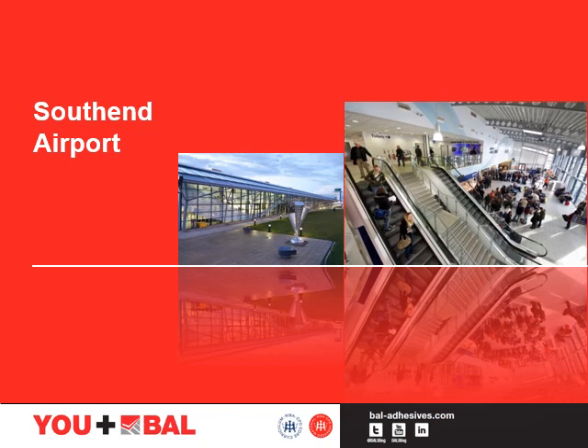London Southend Airport was extended, which included the development of a new departure lounge. More than 5,500 metres of porcelain floor tiles were laid. Floor tiles were laid onto a power-floated concrete finish, a hard-wearing substrate often specified for high traffic areas. Due to the substrate and the heavy traffic use, consideration was needed to ensure that the surface was primed, and flexible, highly polymer-modified adhesives were used in conjunction with flexible, highly abrasion-resistant grouts.